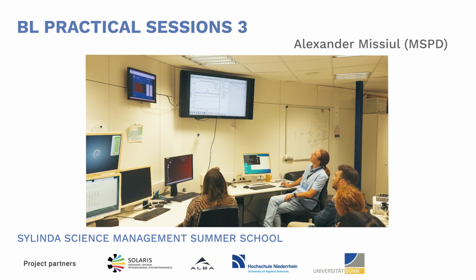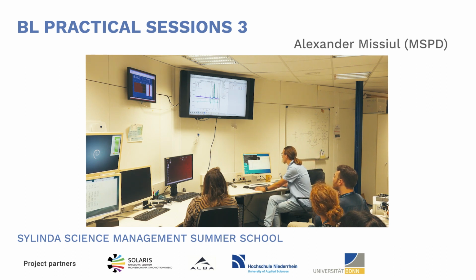So what I will do, I will refine the thermal parameters for all three and position only for oxygen, because for these two it is fixed by symmetry of the unit cell. Let's try to do this. It improves a little bit more, but still not good. Here we start being affected by all these impurities that we did not include. So we import the impurity phases. So copper iron oxide, and we import the Fe2O3.